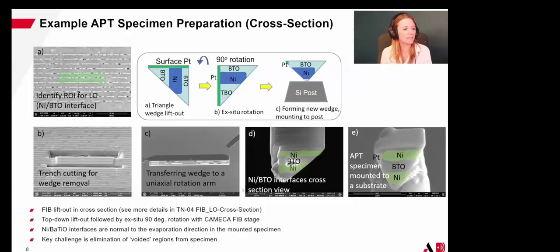The other thing I want to point out in these are the presence of voided regions in the mounted wedge that you can see here in image D. A lot of times these don't extend all the way through your pulled wedge here, so you can just generally skip one mounted chunk if you need to avoid that. A lot of times having a voided region in your tip will lead to low success rates. Cross-section sample prep can be a highly effective way to analyze the interface between those metal and ceramic regions.